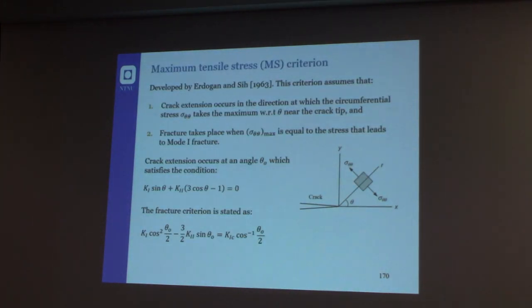It established a criterion that is called the maximum tangential stress criterion. The maximum tensile stress criterion, or MTS criterion, is based on the idea that if you have a crack subject to mixed mode loading, the direction of crack propagation is the direction where locally you have mode 2 equal to 0. So locally the crack tends to propagate in the direction normal to the local stress field, in a condition where you have a kind of equivalent mode 1.